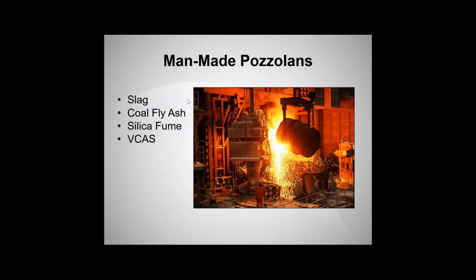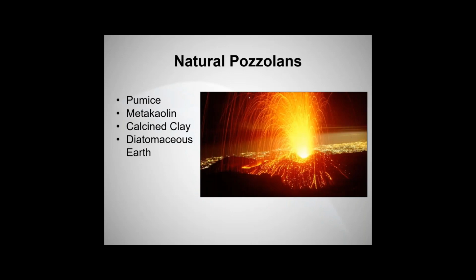What type of pozzolans are typically used? Slag is one of the pozzolans that's used predominantly in the industry. A lot of slag-based ultrafines out there. The coal fly ash, silica fume, and VCAS are not used very often, almost rarely anymore, but slag is definitely one of the man-made components. For natural pozzolans out there, it's pumice. Pumice is used, and from a natural perspective, metakaolin, calcined clay, and diatomaceous earth, albeit they could be used. We almost never see them in the ultrafine cements anymore, but just definitely noteworthy in that regard.